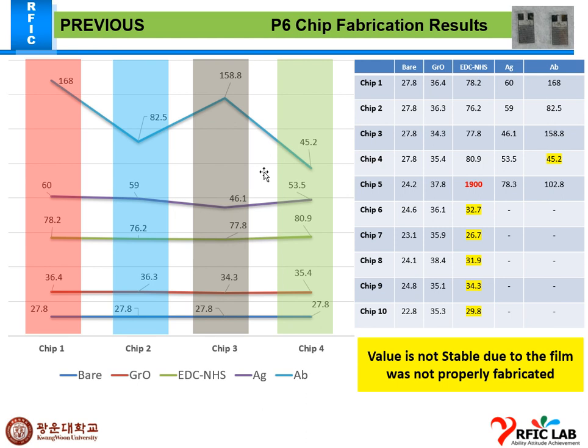And then this one is the result of the previous electrochemical deposition chips, but in this chip I have to conclude that the value is not stable up to the antibody because of the very thin layer deposition, because I ran only 10 cycles on this chip. So that's why I now use 20 cycles in each chip, and it takes 25 to 28 minutes. So I hope we get positive results.